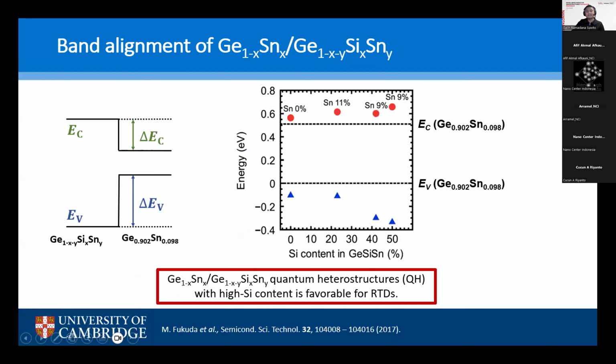Okay. And recently, our group has reported the band alignment of germanium tin and germanium silicon tin alloys. From the figures, you could see how we could design heterostructures by just varying chemical contents. In this case, we vary the chemical contents on these larger band gap layers, and you could see different band offsets in here. Especially for a larger silicon content, you could get quite a large band offset, which is very favorable for RTD because you want to have a sufficiently large band offset in your double barrier heterostructures.